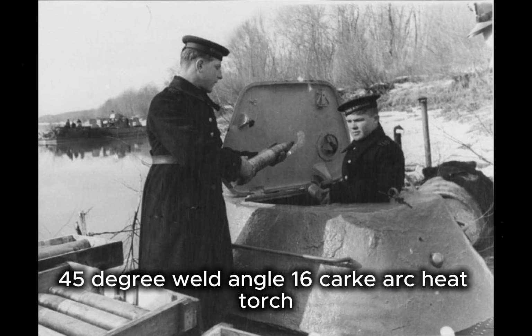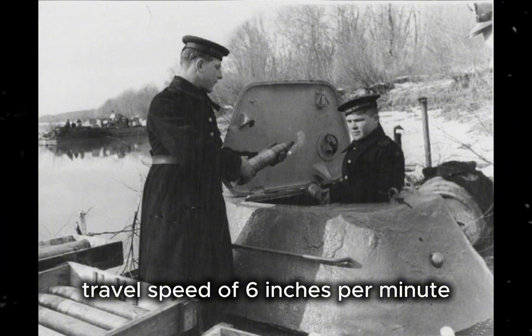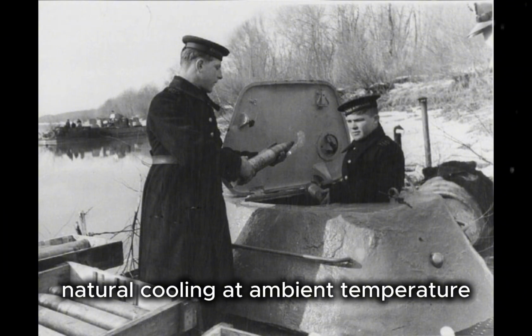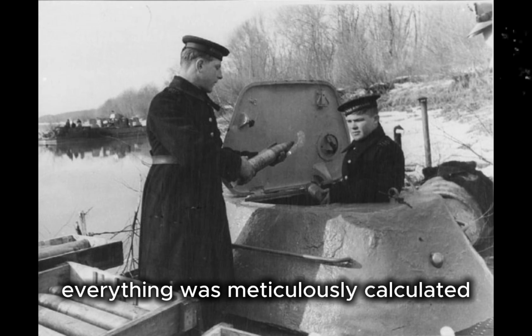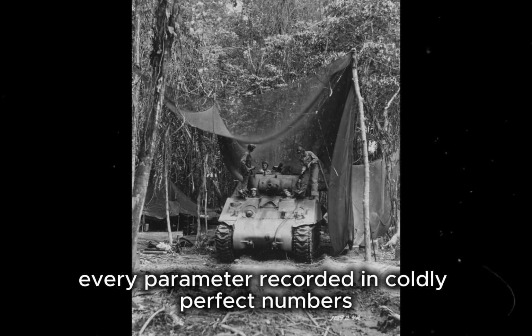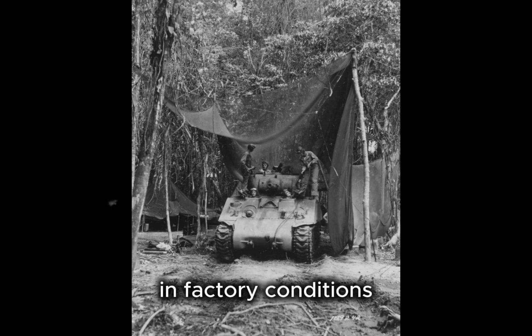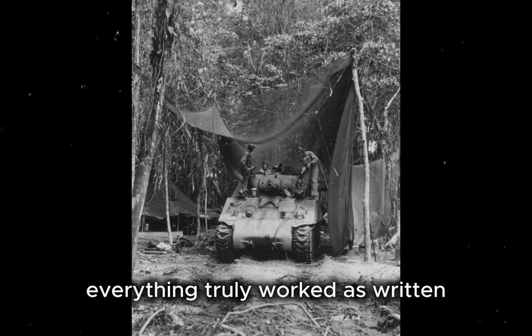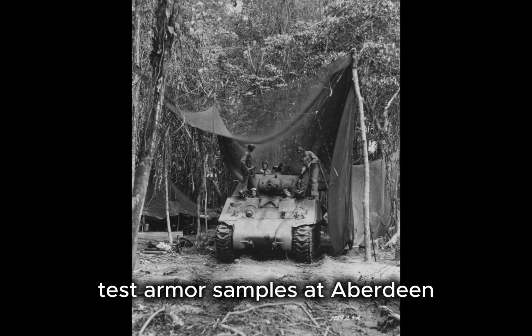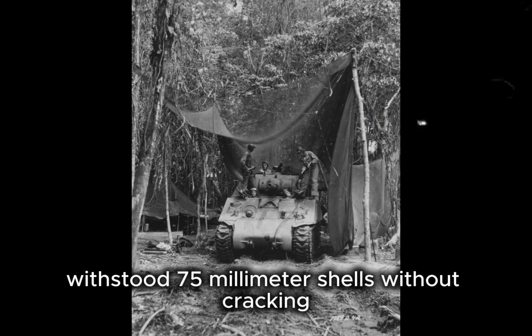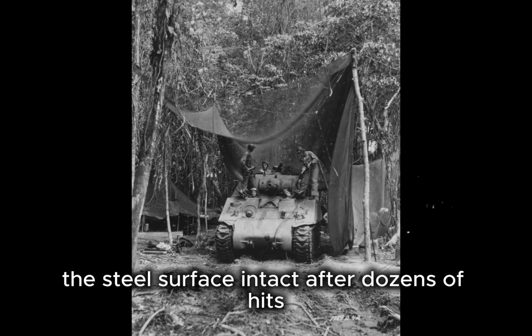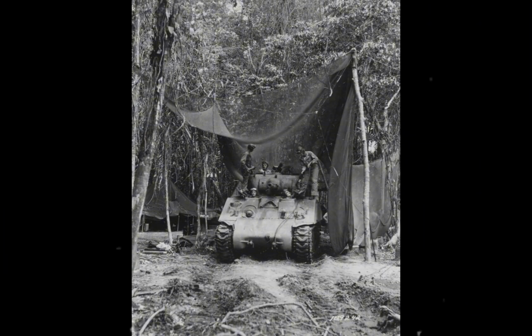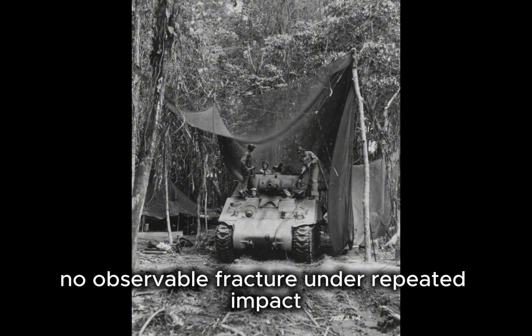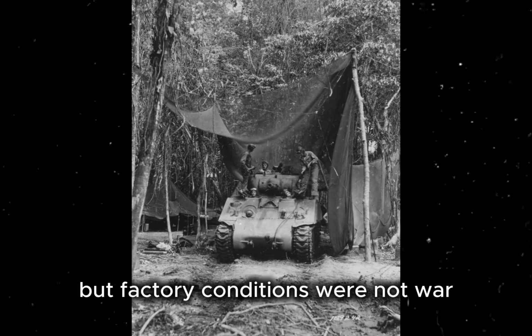45-degree weld angle, 16 kJ/cm arc heat, torch travel speed of 6 inches per minute, natural cooling at ambient temperature. Everything was meticulously calculated. Every parameter recorded in coldly perfect numbers. In factory conditions, everything truly worked as written. Test armor samples at Aberdeen withstood 75mm shells without cracking, the steel surface intact after dozens of hits. Engineers wrote in reports, no observable fracture under repeated impact, but factory conditions were not war.